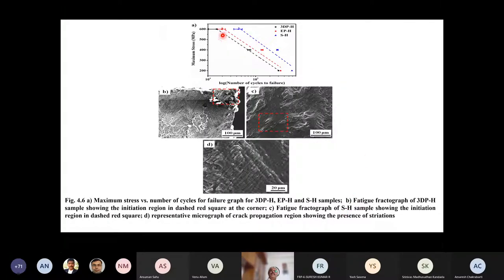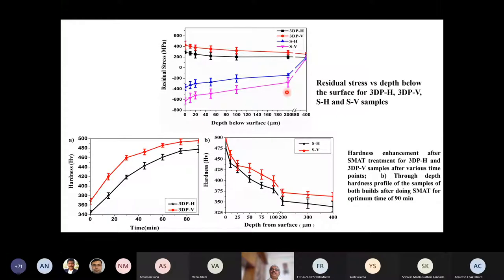So you could see here that we have carried out the fatigue tests on these materials. And actually, this is the result of corrosion fatigue we have done under controlled media, because we wanted to examine biocompatibility, but it will have similar effects on regular fatigue tests also. You could see here that H is the heat treated condition. For all the three conditions, the fatigue life substantially gets enhanced as we go ahead with these treatments, like surface mechanical attrition treatments.